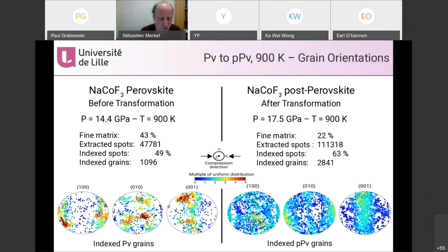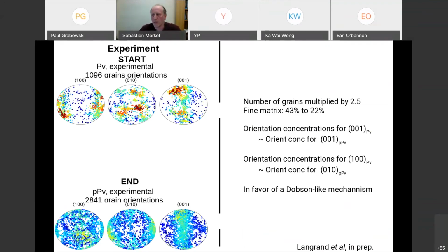So for instance, the first thing we can see when we compare those two distributions is that the number of grains is multiplied by a factor of 2.5. When we look at the orientations of (001) planes, they are pretty much matching between (001) of perovskite and (001) of post-perovskite.